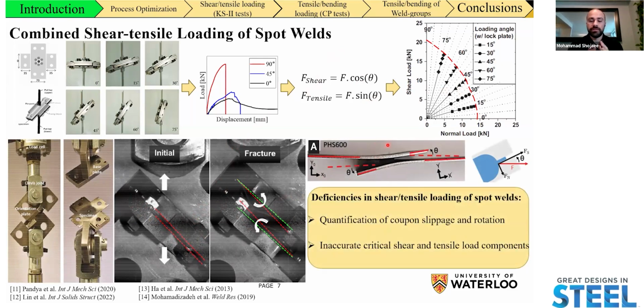So the deficiencies that really exist in terms of characterizing the behavior of spot welds in shear tensile loading is that we are not really quantifying the slippage or rotation of the coupons, and we're having inaccurate critical shear and tensile load bearing capacities at the onset of failure for the spot welds.